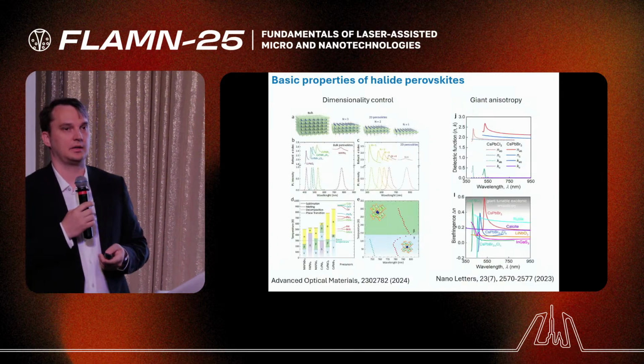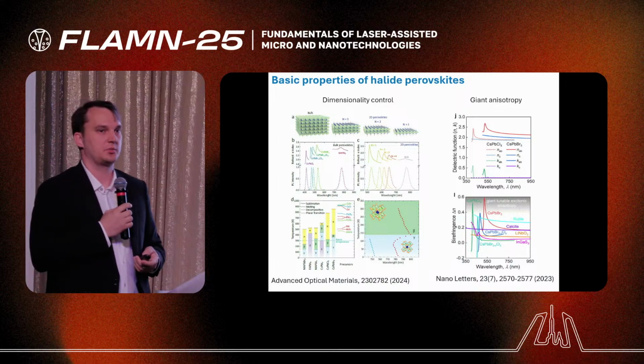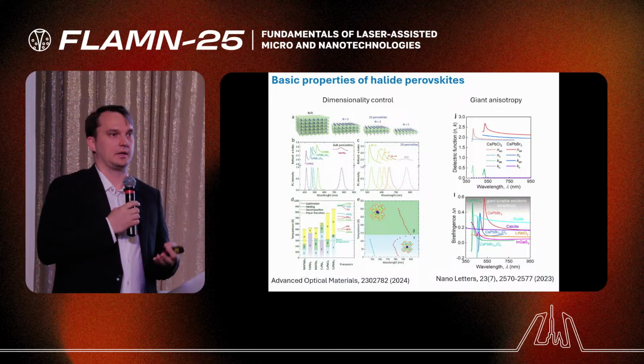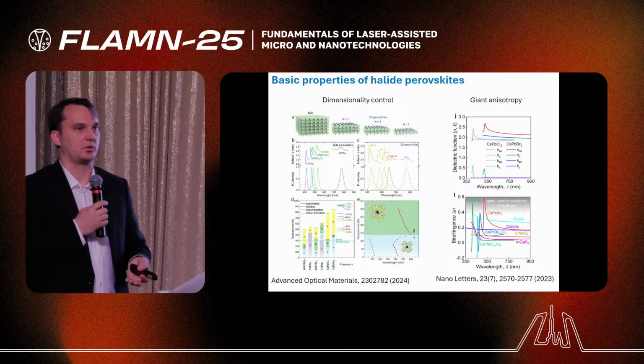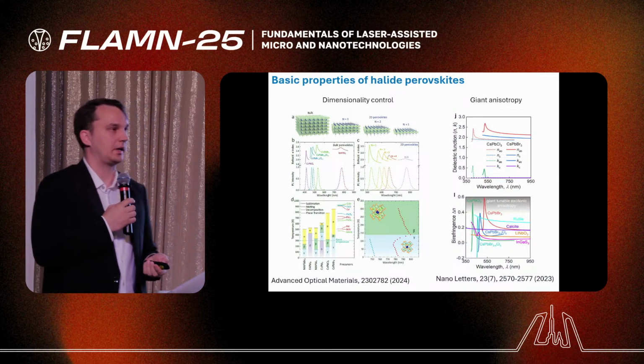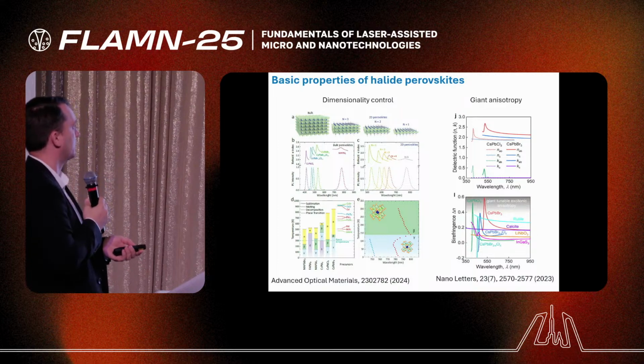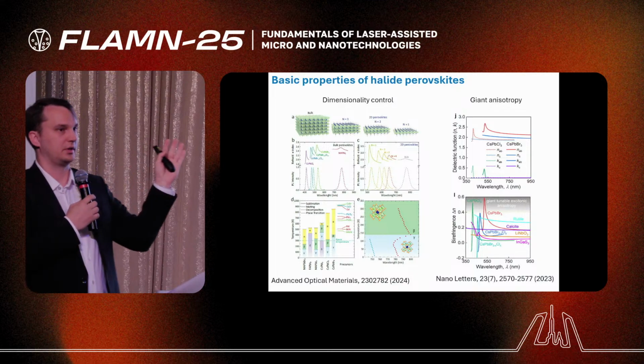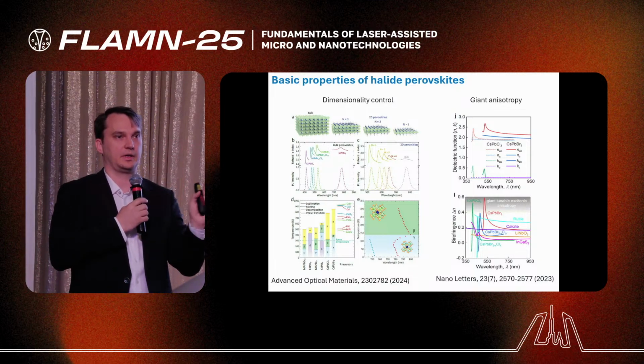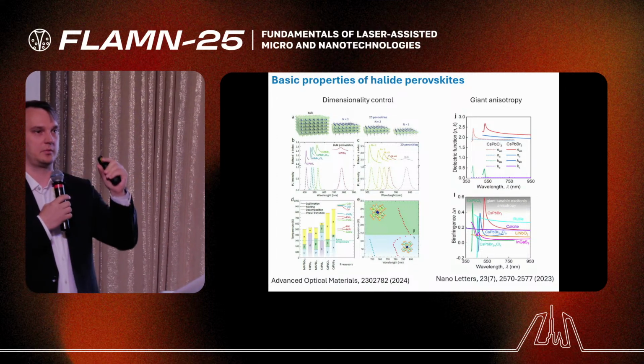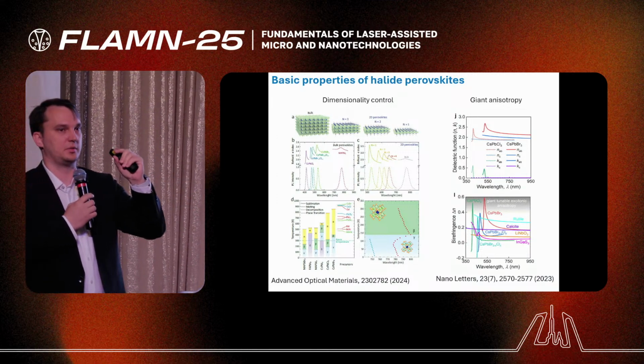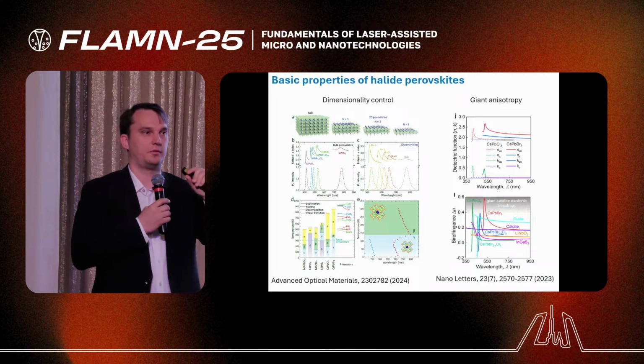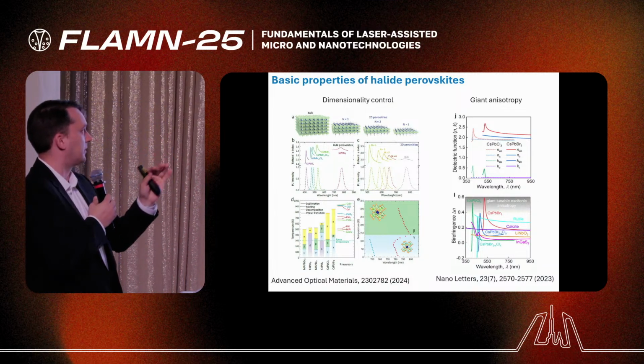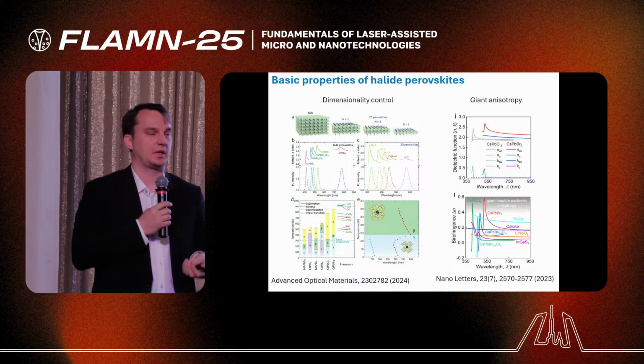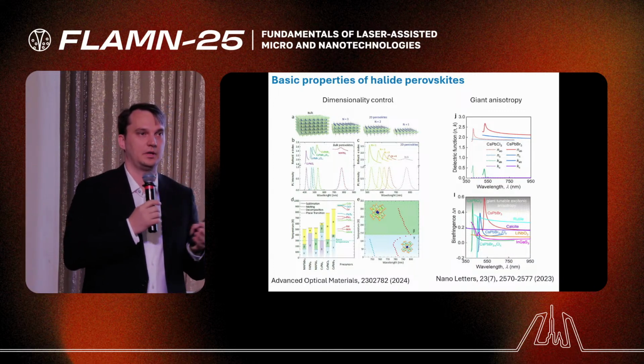Also, there are some interesting properties of such materials. They can be low dimensional, they can be layered, and people call them 2D perovskites. Why is this important? Because we can play not only with the composition of perovskite to tune the band gap and the emission wavelengths in the whole visible range, but also with the thickness of the layers of two-dimensional materials to play with quantum confinement, and also tune the luminescence emission wavelengths in the whole visible range as well.